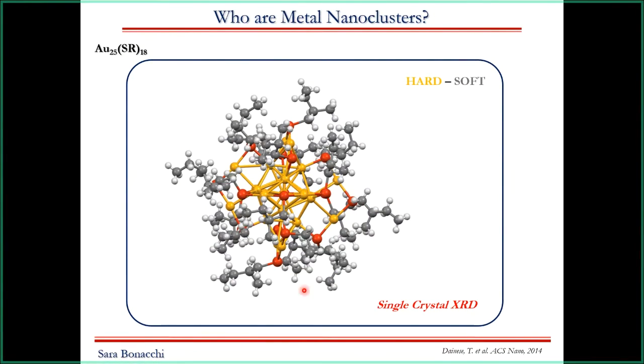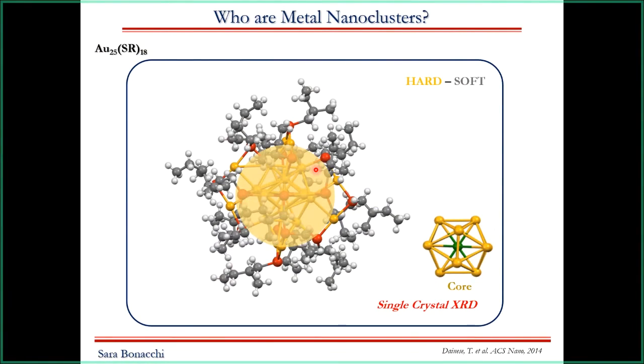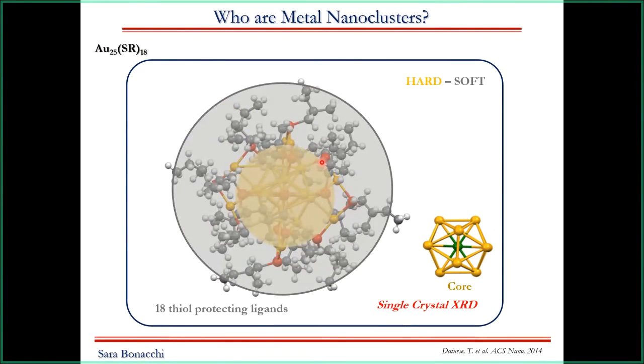Of course, first of all we have to clarify that these metal nanoclusters can be considered as having a double nature, a hard and soft nature, let's say. So, for instance, here I report one of the benchmark nanoclusters, the Au25 nanocluster, surrounded by 18 thiolates, and this kind of cluster, like the others, is characterized by a hard core, made of a metallic core, surrounded by a soft and dynamic organic shell, like in this case thiolates, but it can also be carbene or phosphine ligands that stabilize the cluster, protect the cluster, and also give them different functionality.